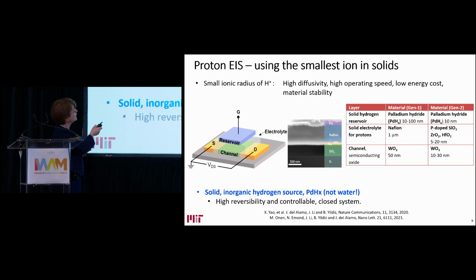So we have focused mostly on proton, as I said a few minutes ago, because it's the smallest ion in solid state, which gives it higher diffusivity, especially in the channel materials that we're exploring, which then, of course, corresponds to higher operating speed that comes with lower energy cost and also least disruption to the material that we are inserting into, which are advantages compared to other small cations, like lithium or sodium or magnesium. But with hydrogen, you need a reservoir where you can store it in solid state, and ideally also it should be the gate for your device.